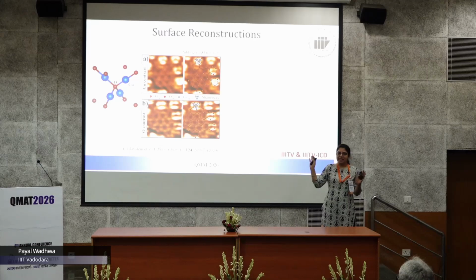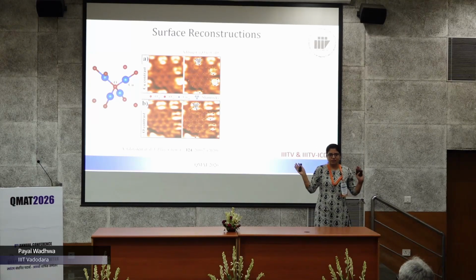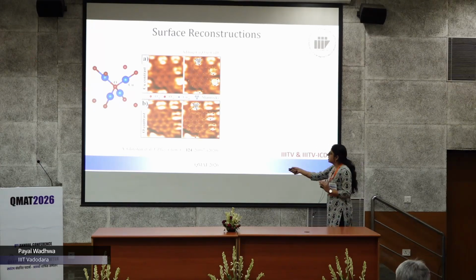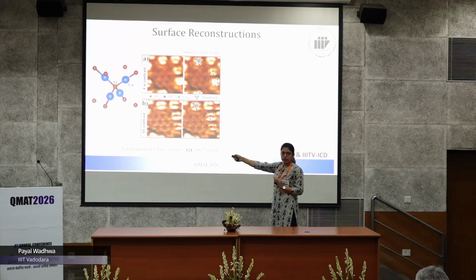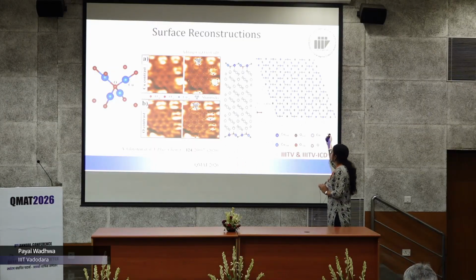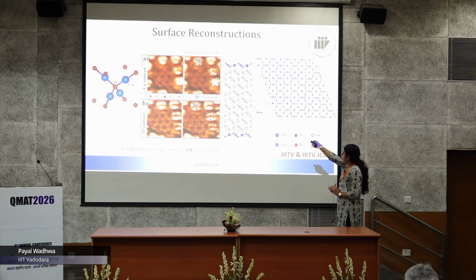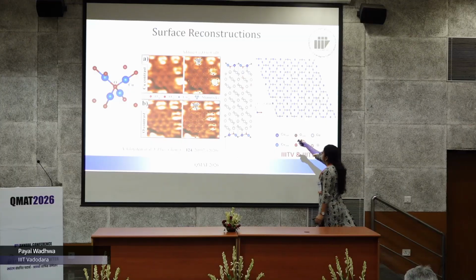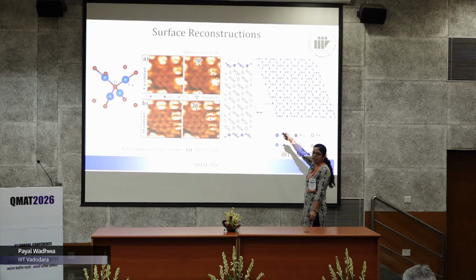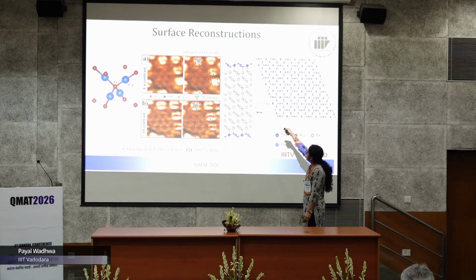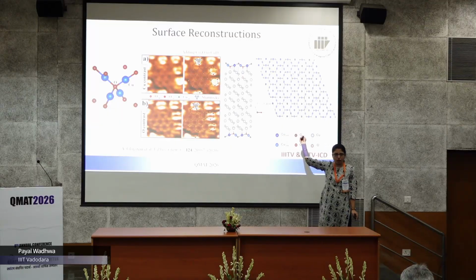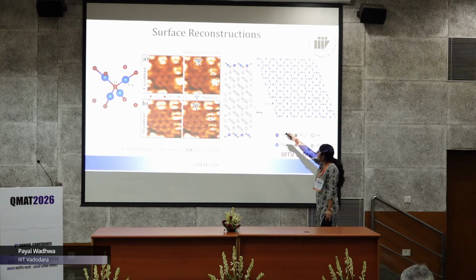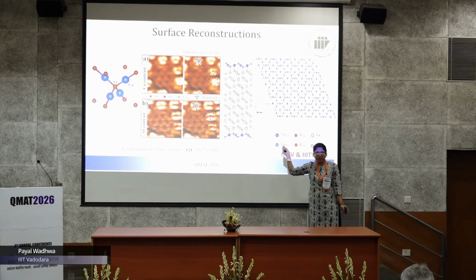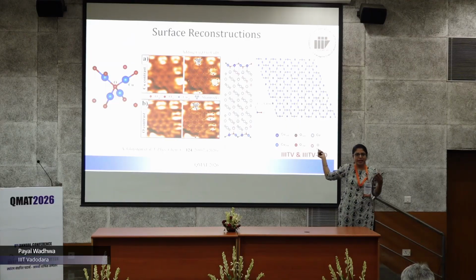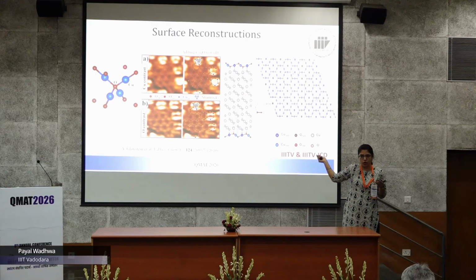So let's see what DFT can suggest out of it. This is the normal bulk structure of Cu2O, and this is its 111 surface. We can see here, of course, when we cut its surface, it will be losing its next bulk counterpart, right? So of course, the atoms on the surface will have dangling bonds, right? So they will not be that stable.